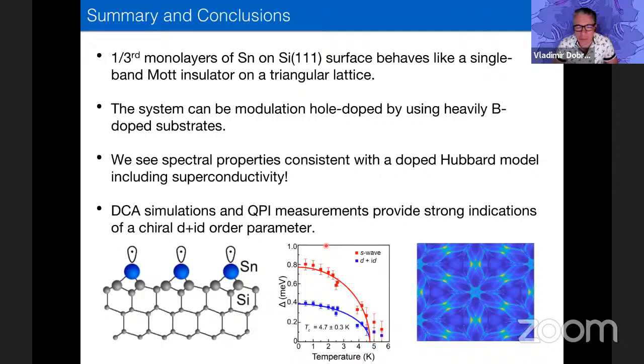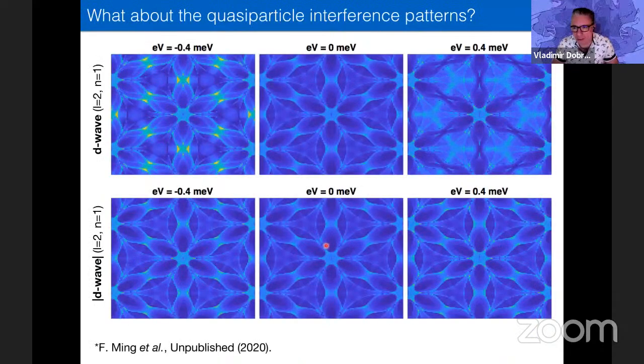So Steve, it was a very interesting talk. I thank you very much. This was kind of an eye opener. This is really a beautiful system, and my question is concerning the QPI story. One of my interests over the years has been what happens when you put impurities, not in non-interacting systems where you get standard Friedel oscillations, but in correlated systems near the Mott transition where quasiparticles can interfere. That was partly stimulated by previous work done by Nandini Trivedi's group and collaborators, which was of relevance to Seamus Davis's experiment, where they originally discovered a phenomenon that they described as healing. We have done some related work in the normal phase, but it boils down to the following. Basically, when you put a particle somewhere, normally you send Friedel oscillations which decay slowly, as you explained.